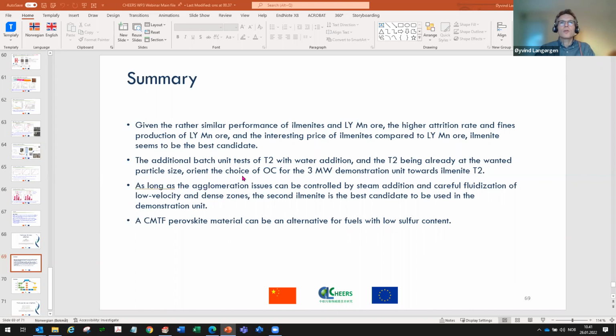And we had 2 alternatives, and the one, T2, which has the more favorable particle size, is the one that is chosen here. Some early problems with agglomeration were solved and could be explained, and we feel more confident that this would work than in the demo unit. The agglomeration issues have, of course, not disappeared 100%. This is still a concern for the demo unit.